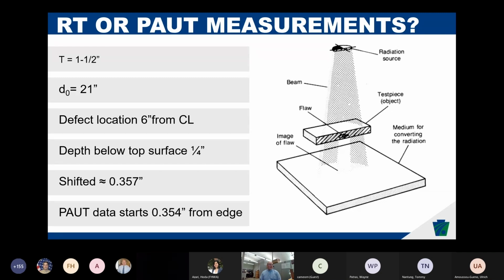With radiography, it was determined that the location the indication actually started from the edge was about 3/8 of an inch. And then you go over to the phased array data, and it's pretty much the same location of where you started picking up the indication. So it probably didn't miss the full length. It probably compares pretty well to the actual radiography indication, or the actual indication without the geometric enlargement.